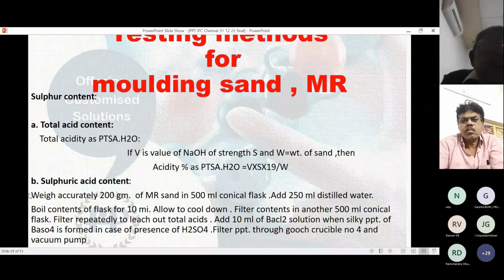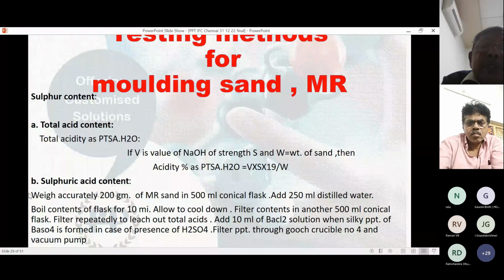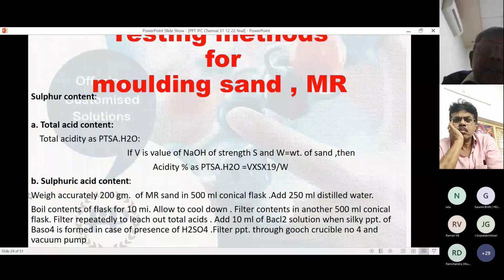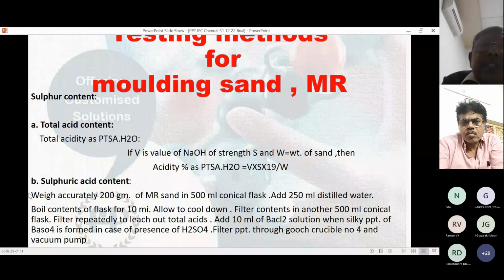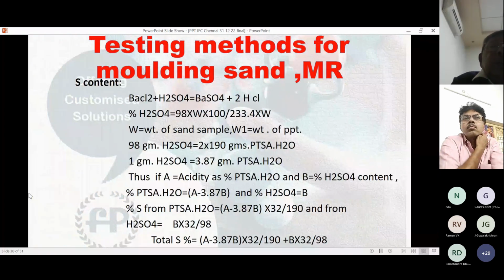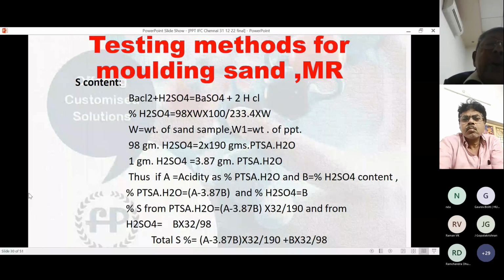Here, first, the sample, like the testing of alkali demand value, is boiled in water and transferred to a conical flask by filtration, where all the acids, including sulfuric acid and PTSA, are water soluble. That will come into the flask. Then you titrate with standard 0.1 normal caustic soda to get the total acidity. And the total acidity you calculate assuming that it is paratoluene sulfonic acid. So from the titer of the sodium hydroxide you can find out how much paratoluene sulfonic acid is there. Now you have assumed that it is only paratoluene sulfonic acid, but it may or may not contain sulfuric acid also. So the next step is that with the same filtrate, you add barium chloride solution.